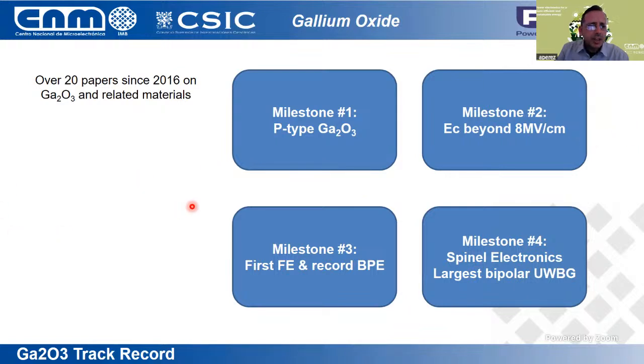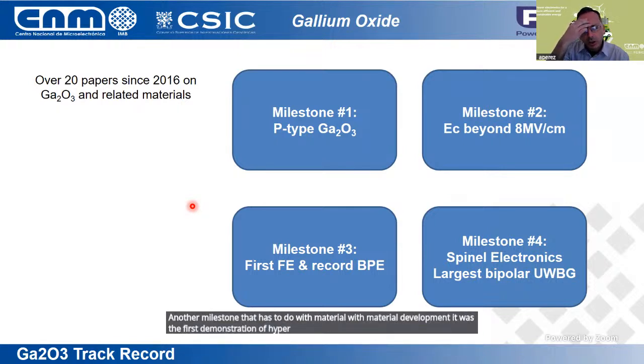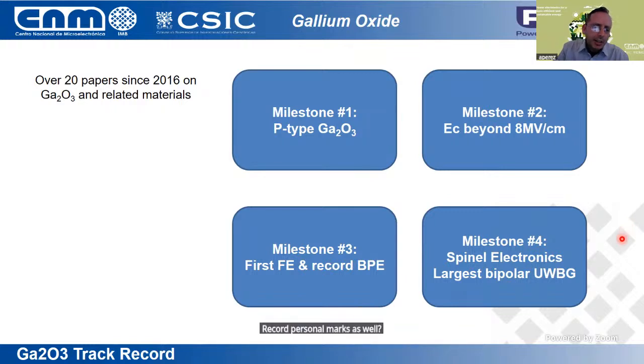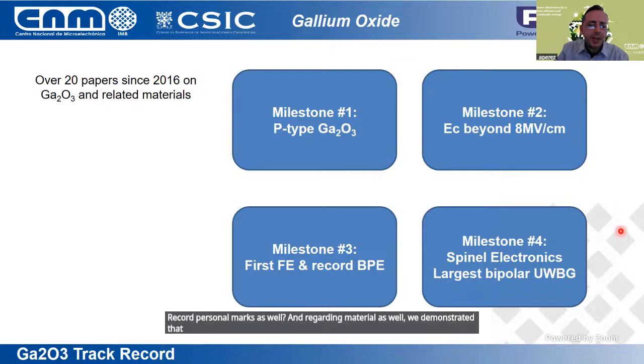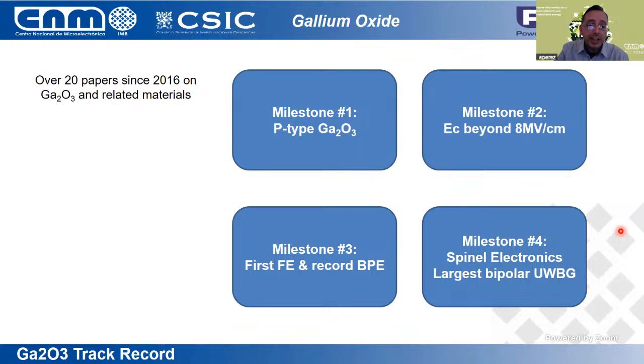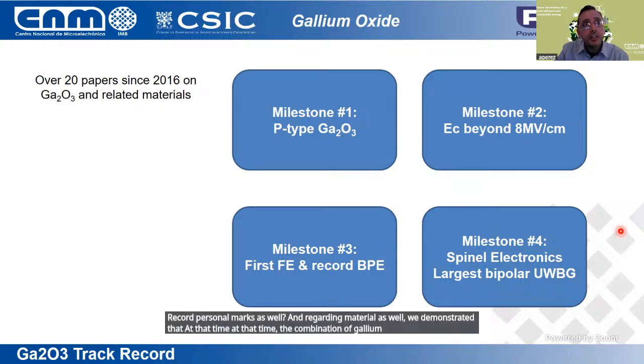Another milestone that has to do with material development was the first demonstration of a ferroelectric grown on top of gallium oxide, and it was applied to a certain kind of solar cell, which is called ferroelectric photovoltaic, so bulk photovoltaic effect, and we got record performance as well. And regarding material as well, we demonstrated that, at that time, the combination of gallium oxide with zinc oxide, which is the spinel zinc gallate, was the bipolar semiconductor with the largest bandgap.